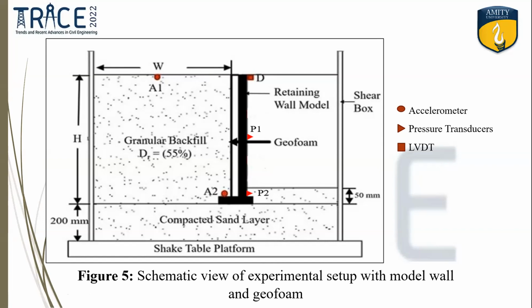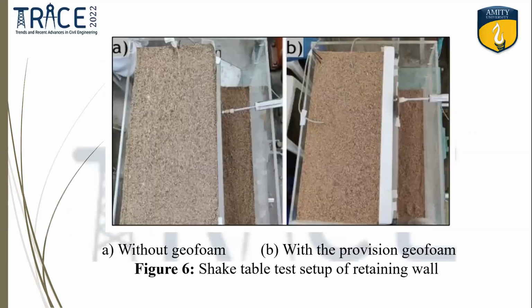At the top of the retaining wall, LVDT, meaning linear variable displacement transducer, are attached to measure the displacement in front side of the wall. The base of the wall is embedded up to the thickness of 50 mm, and at the back side of the wall, the backfill is placed up to the total height of the retaining wall. This is the final shake table setup of the retaining wall without geofoam material and with the provision of geofoam material. The experiment is then repeated with geofoam material behind the retaining wall.